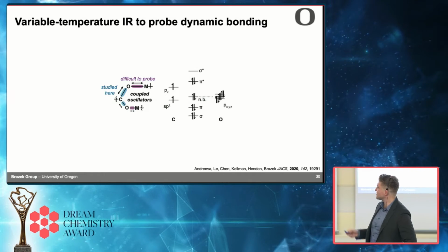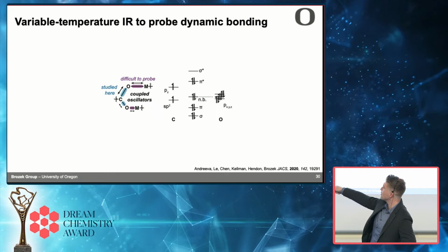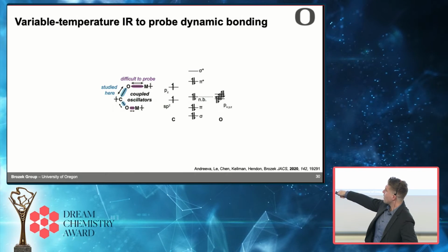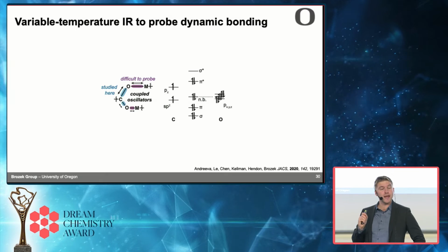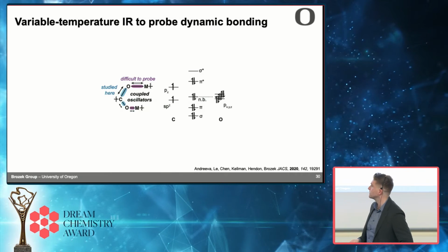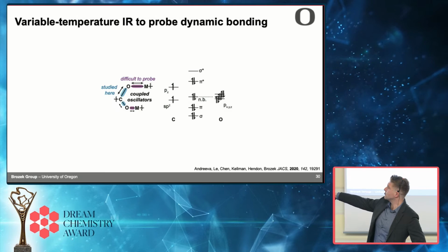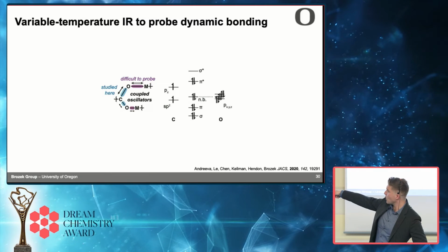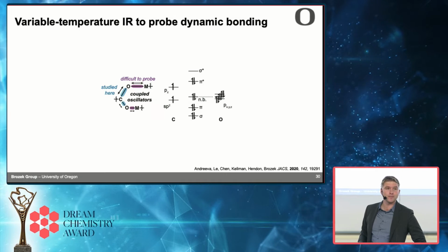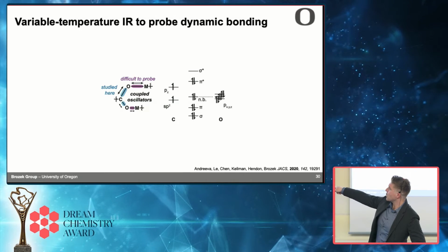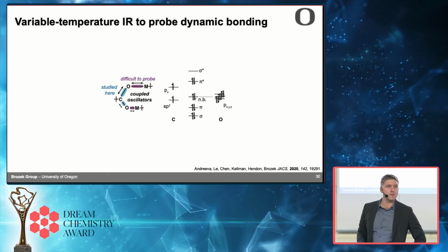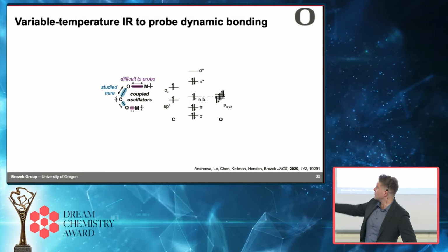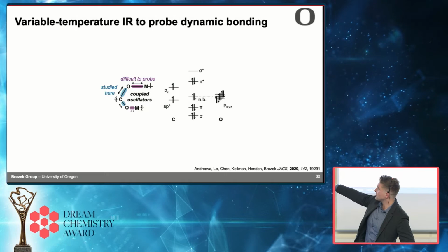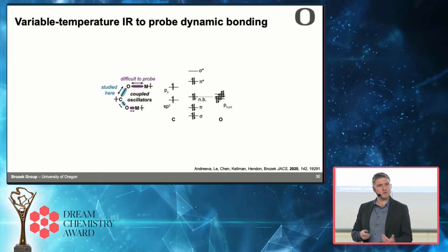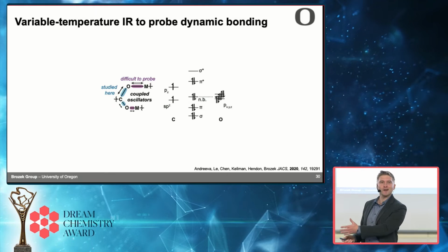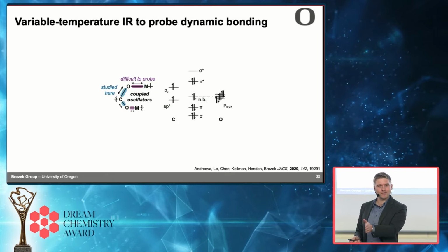The reason I thought that this would make sense, you could justify with MO theory again. So here's an MO diagram for a carboxylate bond. And you have two pairs of electrons that are sitting in orbitals that are formally anti-bonding or non-bonding with respect to the CO bond. These electrons here are the lone pair that sit on the oxygen that form a bond with the metal. And so my thinking was that if you have a really strong bond here, these electrons aren't spending a lot of time in those orbitals, so you have a strong CO bond. But if this bond becomes weak, those electrons are spending more time in these orbitals, and now your bond becomes weaker. In other words, this is a fancy way of saying when you heat up a MOF, the carboxylate bond vibrations should redshift, okay?